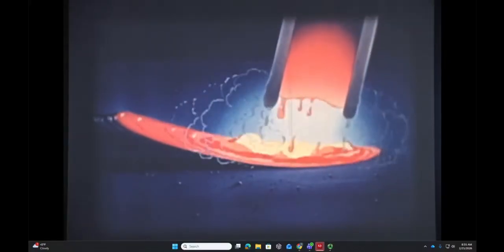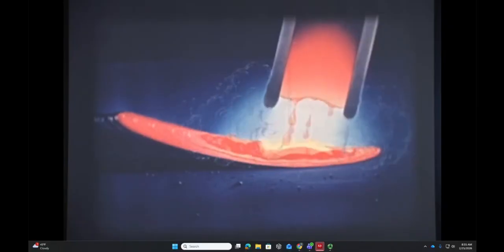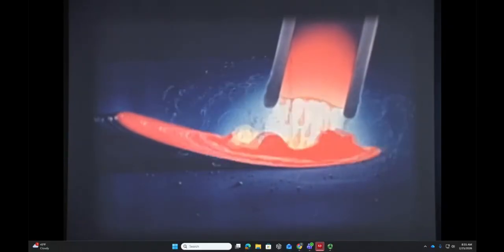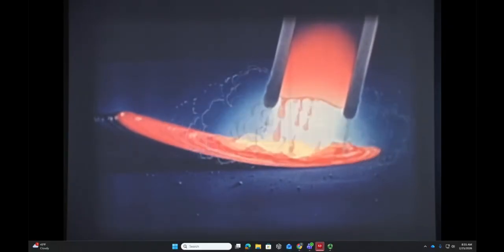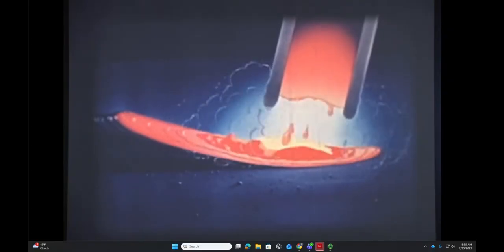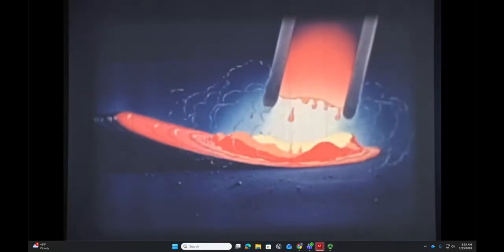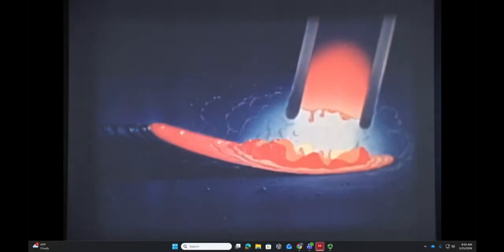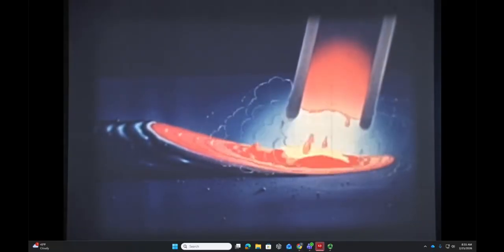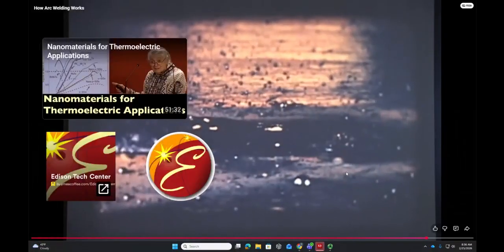A gas is formed, covering the arc with a protective shield that prevents the exposure of the molten metal to the air and therefore prevents the formation of harmful oxides and nitrides in the deposit. Also from the coating, chemicals acting as cleansing agents enter into the metal to help to remove the impurities. These chemicals with the impurities float to the top and, cooling, form a coating or slag over the bead. This slag causes the molten metal to cool more slowly and has an annealing effect.